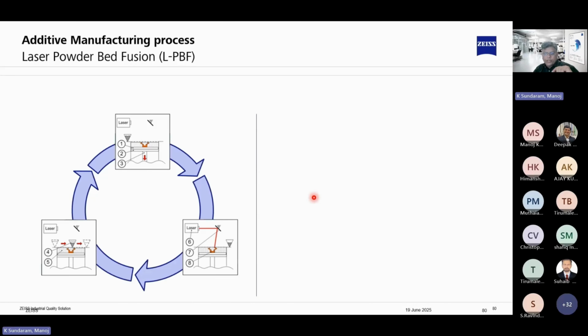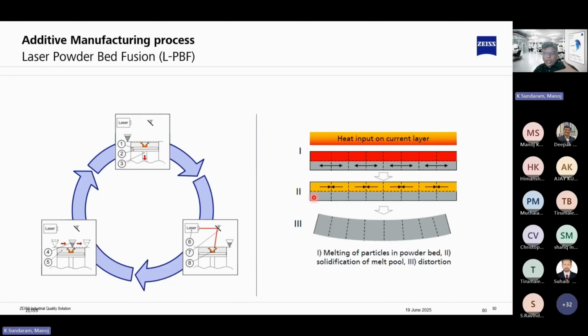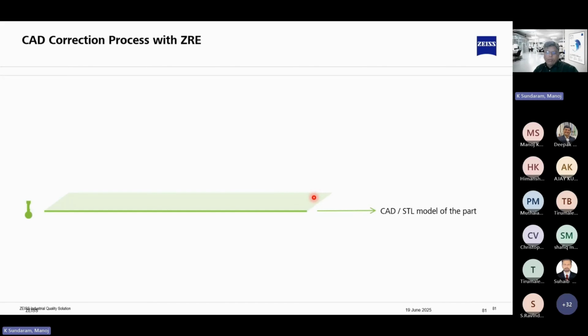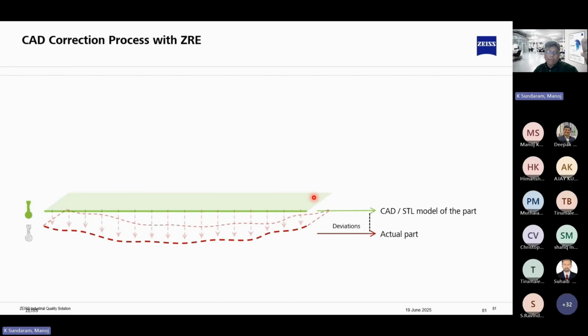Yes. So this is a CAD correction function. It's more required in additive because as you keep heating up the layer on top, there is a warpage which forms at the bottom. So what comes out is not what you desire. There is a CAD model of the part, and then there is an actual part which is getting printed. There is a deviation.